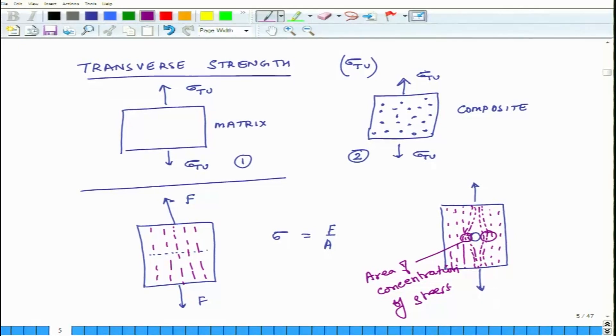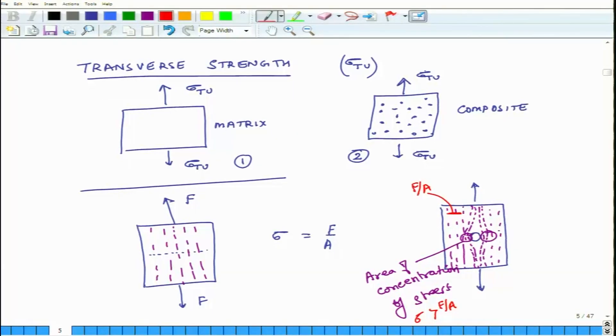What that means is that in a region far away, stress is still F over A, but in the area of stress concentration, stress is more than F over A. So this situation will have higher peak stresses compared to a pure matrix material. As a consequence, a material with even a single solid inclusion will tend to fail at an earlier level. In the case of composites, there are several such inclusions in the system.